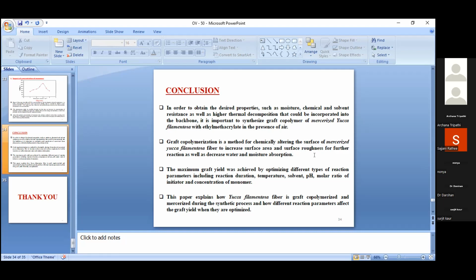The maximum graft yield was achieved by optimizing different types of reaction parameters, including reaction duration, temperature, solvent, pH, molar ratio of initiator, and concentration of monomer. This paper explains how yucca filamentosa fiber is graft copolymerized and modified during the synthetic process, and how different reaction parameters affect the graft yield when they are optimized. Thank you.